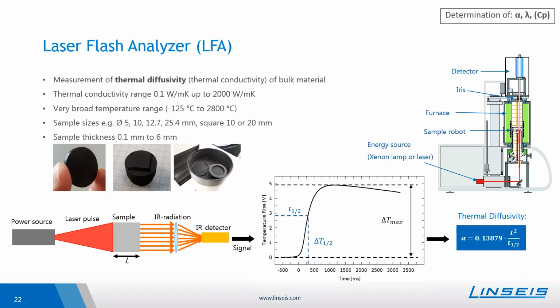The samples typically have a disc shape or a rectangular shape in the order of about 10 millimeter to 1 inch. And the sample preparation is quite easy. You prepare your sample according to the requested size for the sample holder, and then both sides of the sample are covered with a very thin graphite layer. The use of that I will explain in a minute.